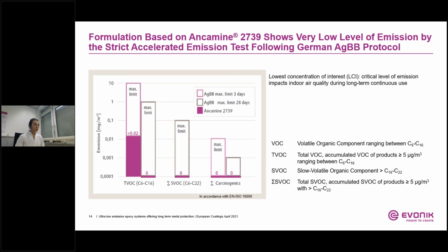As a result of this extremely low level of emission, a second measurement was performed after 28 days. Here, no VOC, no SVOC or carcinogenic substances could be detected after 28 days. Those results clearly demonstrate that the coatings based on Ancamine 2739 curing agent would pass the AgBB test. And in this case, it can be categorized as an ultra-low emission coating system.